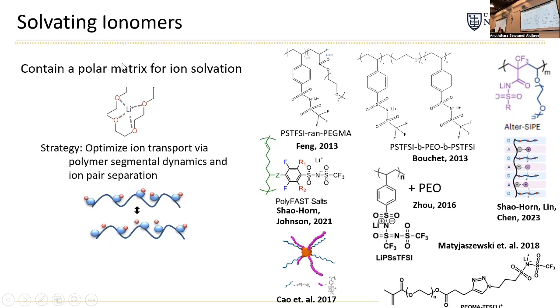So if the PEO chains come closer, because these R groups like them, then the lithium is easily able to go into the polymer. And then the other advance that was made is this one shown here that was published, I think, in Nature Materials last fall. What this group made was, instead of block copolymers or random copolymers like a lot of these polymers, they actually made a perfectly alternating polymer. And so they were able to place every single anion directly near this PEG chain. So again, they put the ethylene oxide units very, very close by to the lithium, and then it's able to be separated and then it moves.